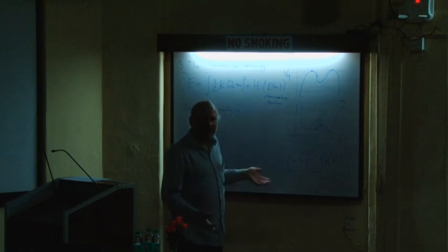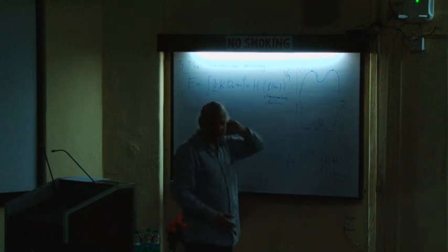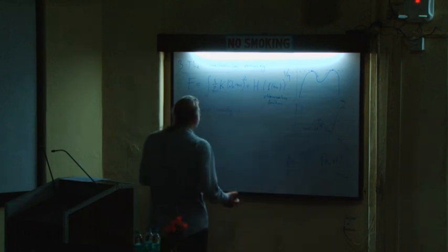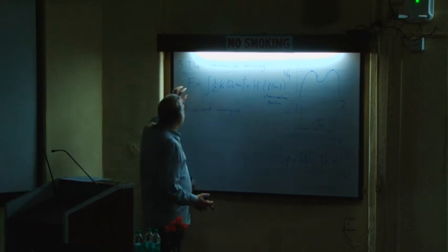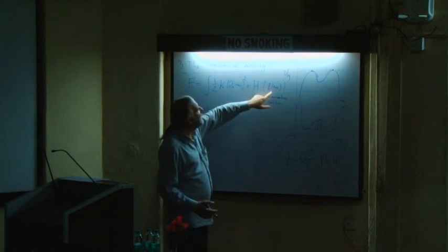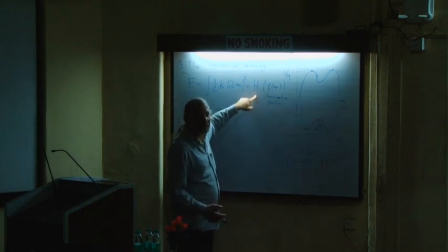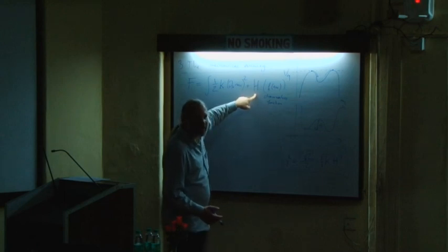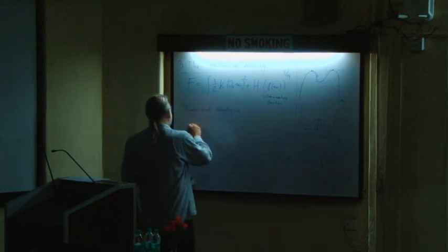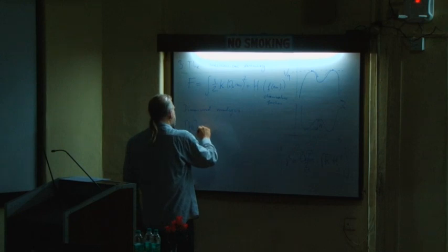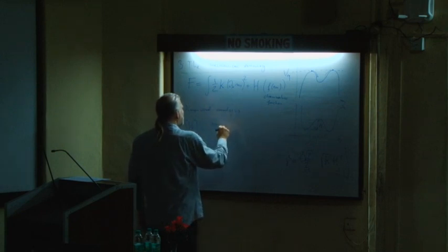So you can look at what are the physical dimensions of these constants and see what you can do with it. Now, we have already had that before. F is an energy. If the little f here is a dimensionless function, that means the constant h has dimension of energy per unit volume. So the dimension of h is energy per volume,